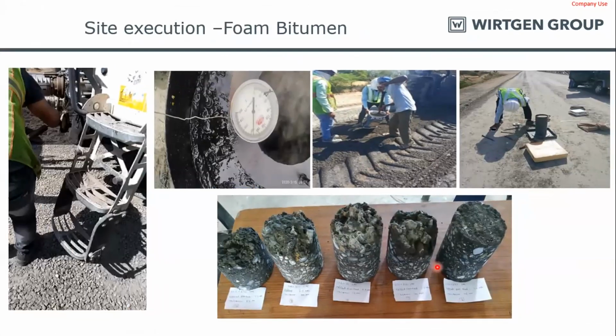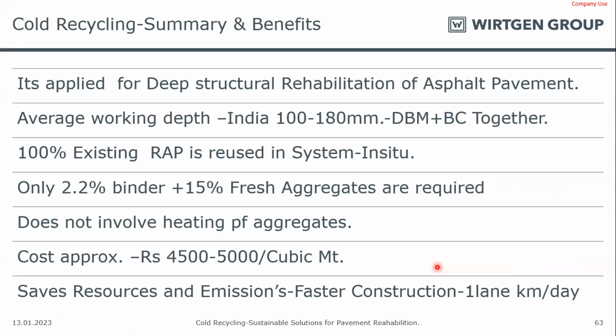These are some of the pictures from the site execution. So we check the bitumen temperature, and also we check the expansion ratio and half-life. We check the bitumen which is being injected to the machine, and also we check the density in the field. And after the existing layer is relayed, we take the samples for evaluation in the lab.